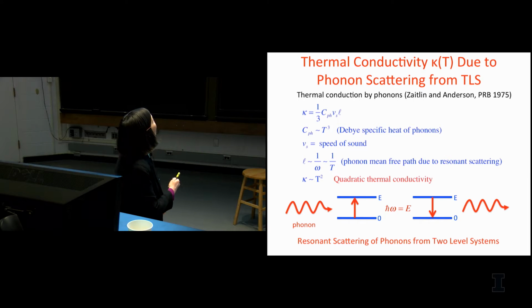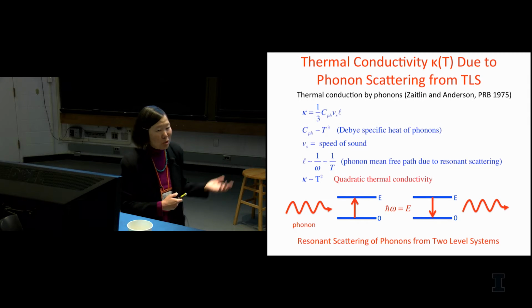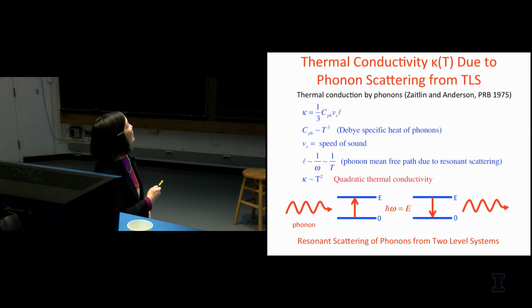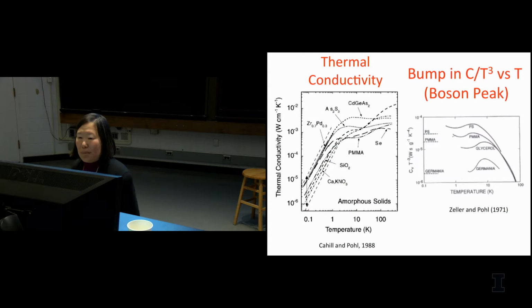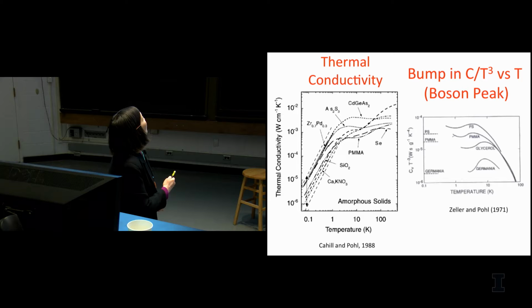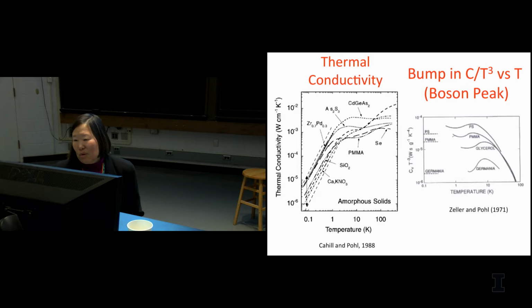And the mean free path, in this case, is going to be limited by resonant scattering of the phonons from the two-level system. So when the phonon energy matches the two-level system energy, it would be absorbed and later re-emitted. And that then gives you quadratic thermal conductivity. OK, but what about this plateau in the thermal conductivity that's bumping the specific heat? What do we do about that?